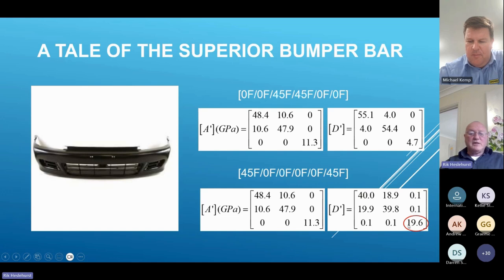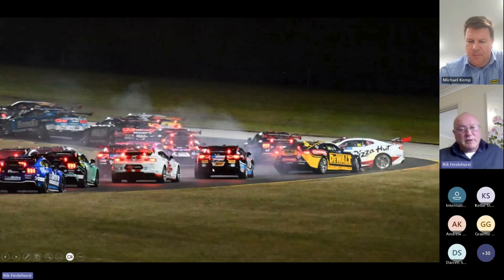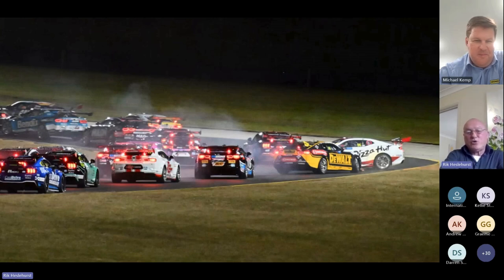But the torsional value has gone up almost 5 times by just changing the position of those plies. So what does that mean? Well, in V8 supercars, a lot of love taps occur during the race, and typically to bumper bars. And a bumper bar could be dislodged, but not necessarily come off. And you would be technically black flagged to come in and replace the bumper bar.